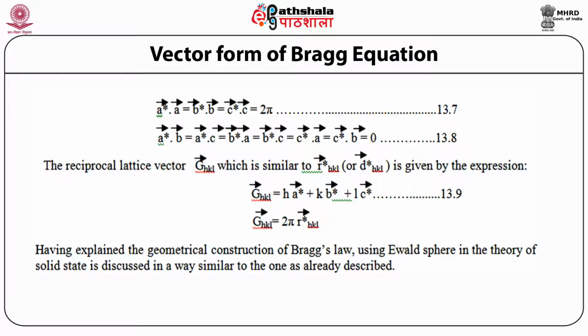which is given as equation 13.8. The reciprocal lattice vector G HKL vector, which is similar to R star HKL vector or D HKL star vector, is given by the expression capital G HKL vector is equal to H A star vector plus K B star vector plus L C star vector, given as equation 13.9. So G HKL vector is equal to 2 pi R star HKL vector.